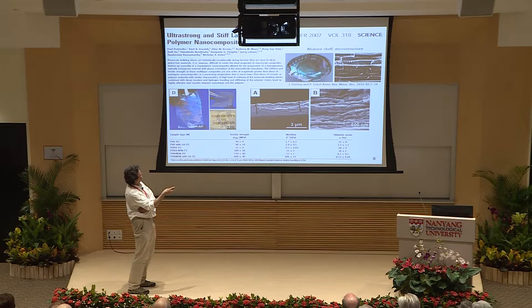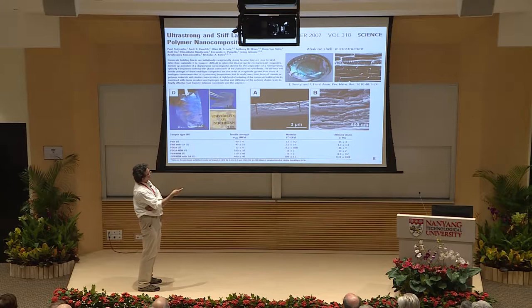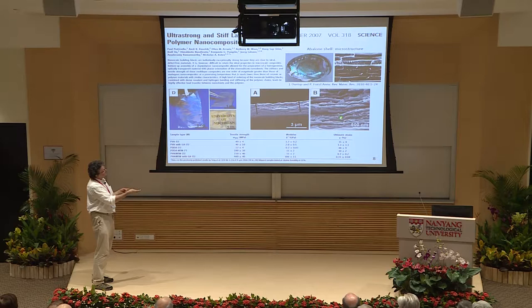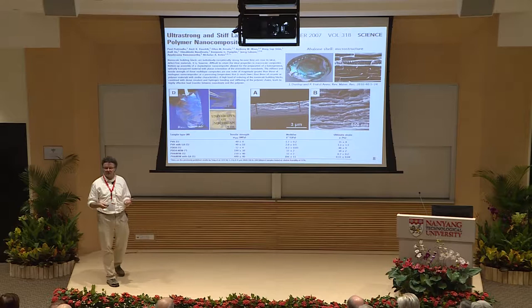That work was modeled after the abalone shell, which has a brick-and-mortar structure. This structure was reproduced by layer-by-layer. Nik ended up with a tensile strength of 400 MPa — that's the value to beat. He used Montmorillonite, which is fine, but we set out to beat that figure using biodegradable components.